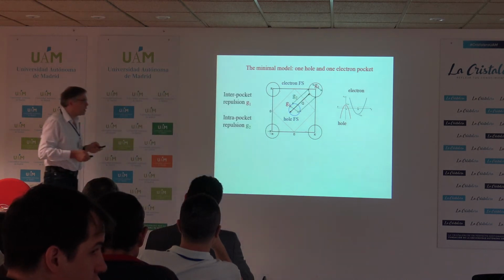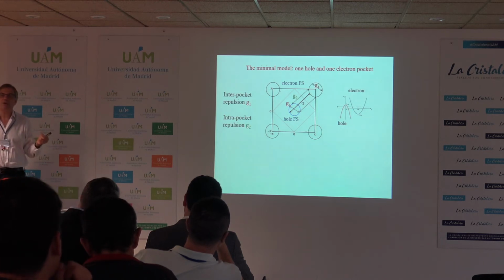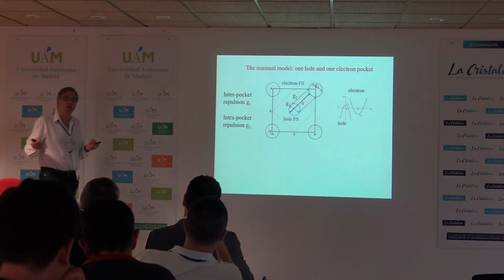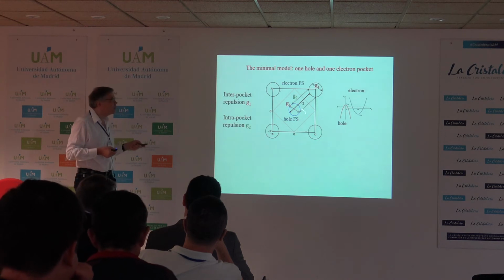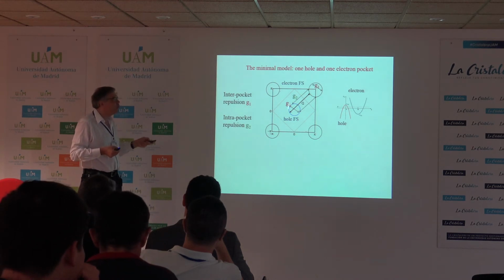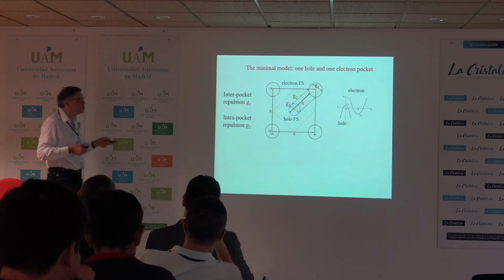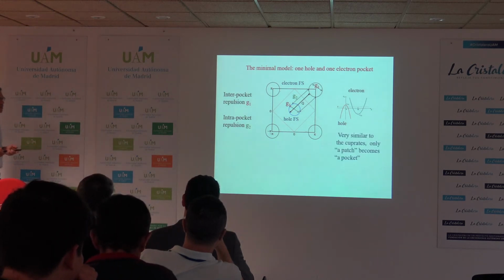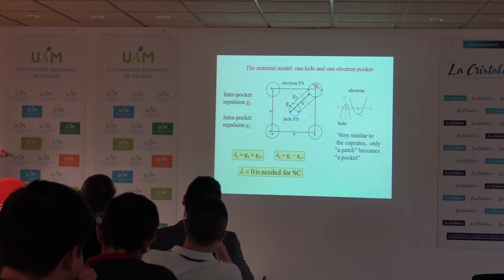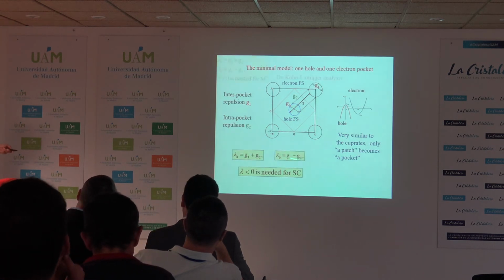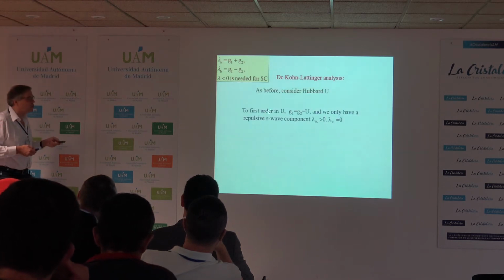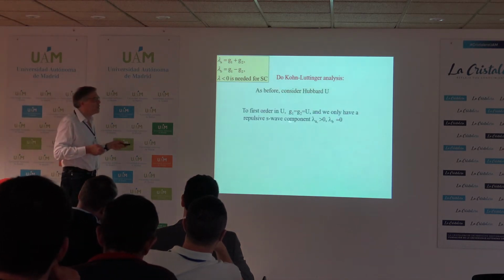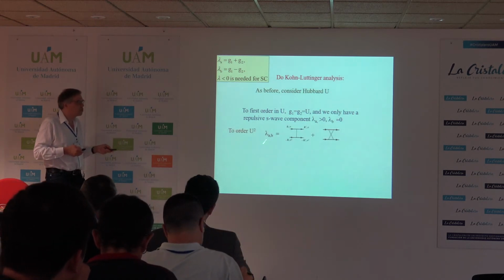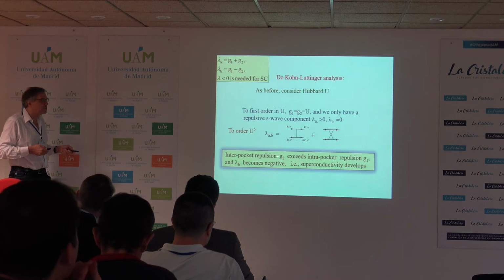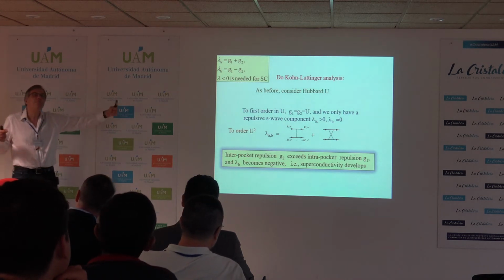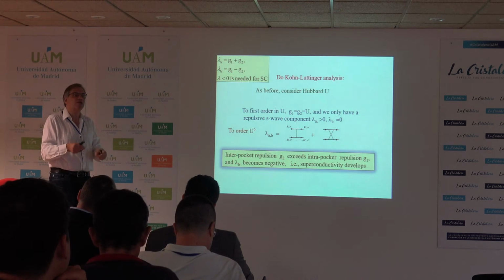Then you can ask yourself, well, what if I do exactly the same stuff, only instead of patch, I now use the word pocket. So I have again interaction within one pocket, I have interaction between pockets, I call them the same way G1 and G2, and I do exactly the same reasoning as for cuprates. Again, two channels, two coupling constants, I need negative lambda for superconductivity. I go to Hubbard model, same story. One interaction is zero, another is repulsive. I do second order perturbation theory, and I get the same result. That interaction between pockets now becomes larger than interaction within pocket.